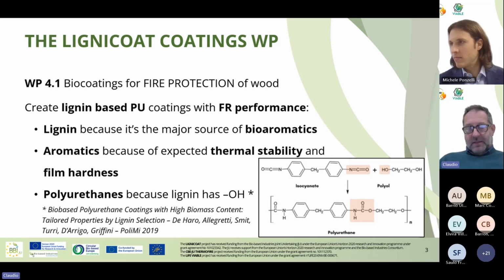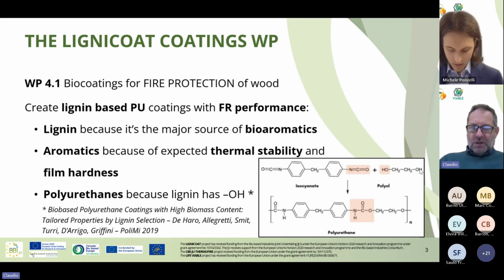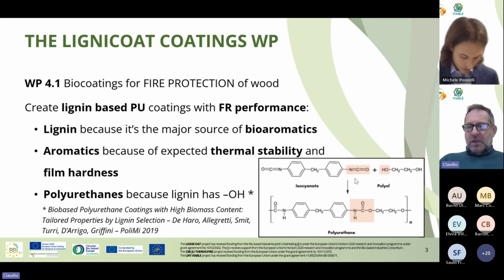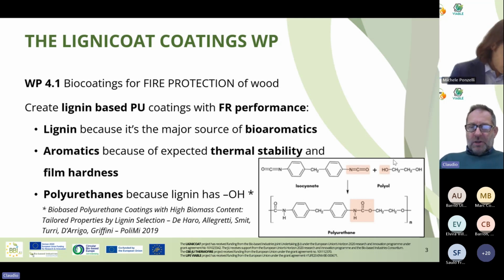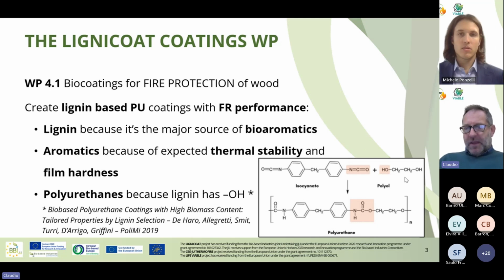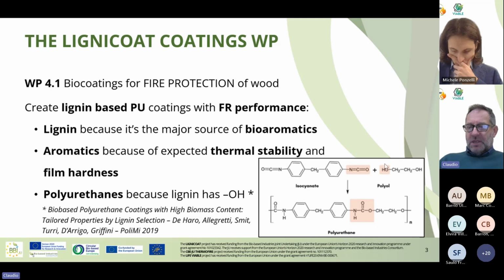Why polyurethanes at the end? We went through some work and we came to this idea at the end. Lignin has quite a large number of hydroxyl groups. You have seen the molecule before. This polyol here in my picture, of course, is not lignin. What you need to make a polyurethane is at least a difunctional isocyanate, so a molecule including two NCO groups, and a molecule including at least two OH. The reaction of these will give the urethane link and a molecule more or less of this kind. Well, lignin is rich in OH, and we can expect it to perform this function.